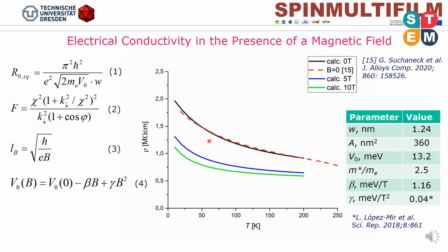Now, the resistivity of strontium ferromolybdate was calculated in dependence on the temperature T and the magnetic flux density B. The parameters used for calculation are compiled in this table. The figure shows also a comparison with a zero field resistivity with our recent measurements on nano-size granular strontium ferromolybdate, strontium molybdate samples.